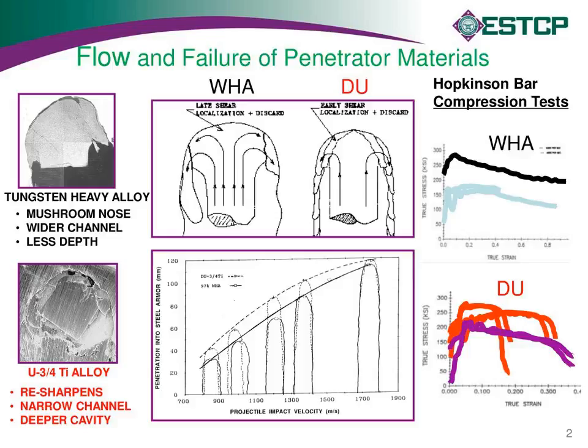So the test is sort of being interrupted at that point by that plastic instability and localization, the adiabatic shear process, versus the tungsten heavy alloys. Again, they're stable during that whole deformation process, and the sample remains load bearing during the whole event. The axes on those plots are actually different. The DU ones go out to about 30% strain. The tungsten heavy alloy plots go out to about 100% strain. So the big difference is in plastic stability and shear banding in an instrumented test.